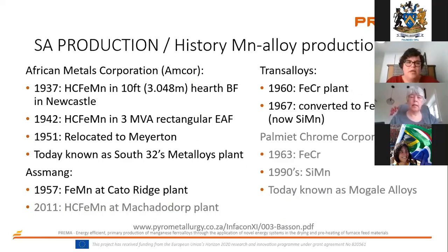So, as I said, Amcor was established in Newcastle in 1936. They started to produce high carbon ferromanganese using a blast furnace. And then in 1942, a 3 MVA rectangular electric arc furnace was built. That's the same size as the largest furnace at Mintek, and that was used for the production of the alloy, so it was a production furnace. In 1951, they relocated to Meyerton, and today it is South32's Metalloys plant. Assmang was established in 1957 in Cato Ridge near Durban, and in 2011 they converted the Machadodorp plant also to high carbon ferromanganese production, but that plant has been mothballed.